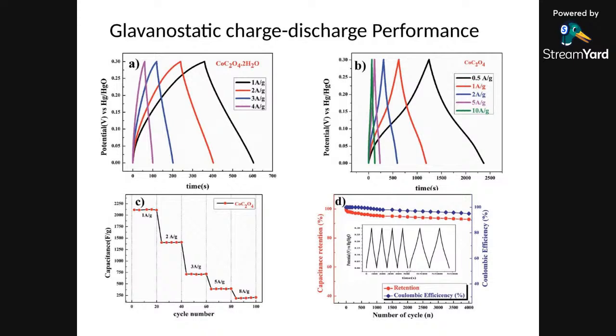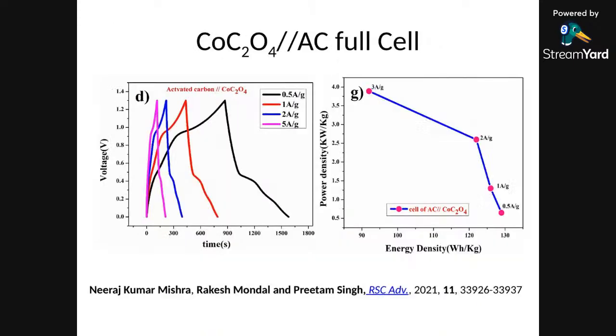So we are reaching up to that extent using this cobalt oxalate, these nanorods. And then we have done the full cell performances. See, now in the full cell, we can get a much higher plateau. So then we are actually tending more towards the battery type of behavior, even though we are using the capacitor kind of